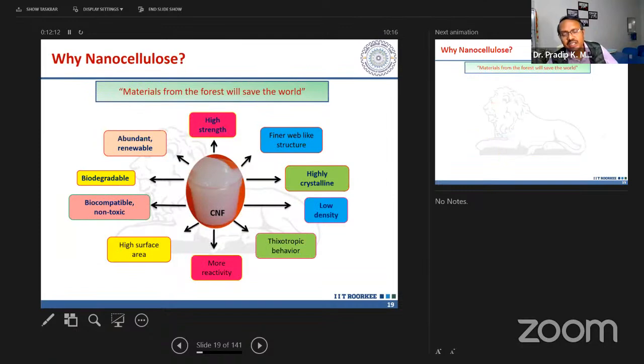Okay, and why nanocellulose? Why will we be using nanocellulose as a material for our application? Because it has very high strength. Mechanical properties are more than 3 gigapascal at the nano level. We have the simulation, and we have checked with the atomic force microscope that it is very high strength. Fiber-like structure, high crystallinity, low density, thixotropic behavior. Then more reactivity due to the presence of OH groups, that gives you the tuning point to do any modification. After the modification, you can utilize whatever functional group you want on this material. High surface area because it's nano. As it originates from the plant, it is biocompatible and non-toxic. Definitely it is biodegradable, abundant and renewable. All those things help us to say that material from the forest will save our world.